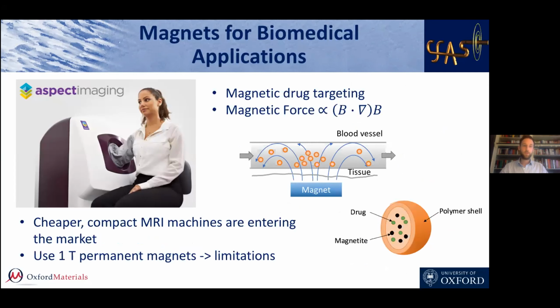So why do we work on MgB2? Well, in my case, we want to make bulk superconducting magnets. And the two important applications here are small compact MRI machines. At the moment, these are entering the market with permanent magnets. Although this is problematic because permanent magnets, as in ferromagnets, have limitations in terms of field capability. So you can't really go past 1.5 Tesla. And this limit, which is inherent to ferromagnetism, we can overcome, because the way the field is generated in superconducting magnets is very different. And so we don't have that limit. We can go, in fact, to much higher field. And we have achieved quite recently almost 3 Tesla in a conventional MgB2 bulk, in fact.